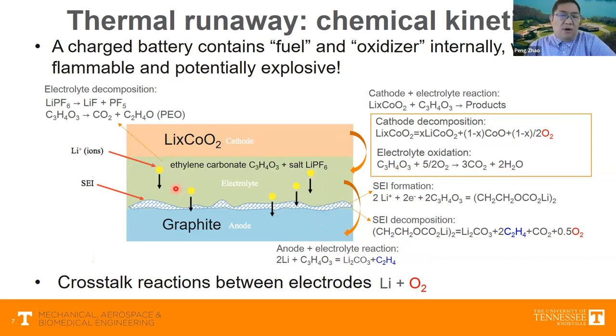And furthermore, this organic component in the electrolyte and also salt can decompose by themselves. Overall, these reactions can release a lot of heat and they generate lots of flammable gases and even have oxygen there, right? And recently people have shown that there can be crosstalk reactions between the electrodes. So that means your lithium in the anode can react with the oxygen that's being generated from the cathode decomposition.